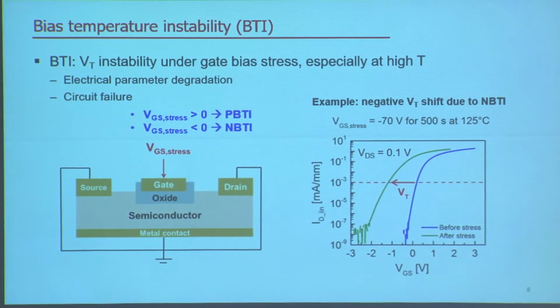And on the right-hand side, what you see is an example of a negative VT shift as a result of NBTI when we apply a negative 70 volt stress on the gate for 500 seconds at 125 degrees C. From this IV characteristic, you see that before the stress, the device is mostly off at 0 volt, but after the gate stress, the threshold voltage has shifted about -1 volt to the negative direction, and now at 0 volt, the device is no longer off. If we're talking about power circuits, that's very unsafe, and it's very bad for circuit performance. So as you can see, BTI is very important for us to address in order to have reliable performance of circuits.